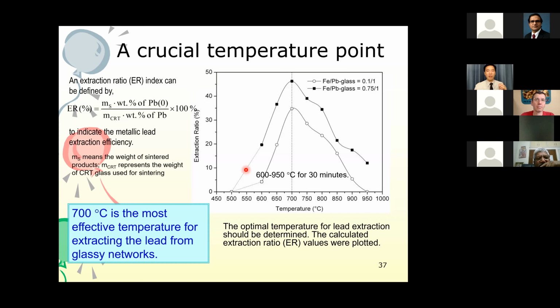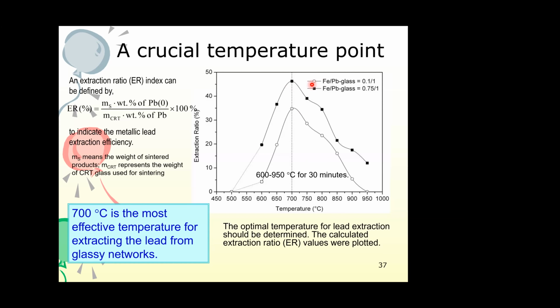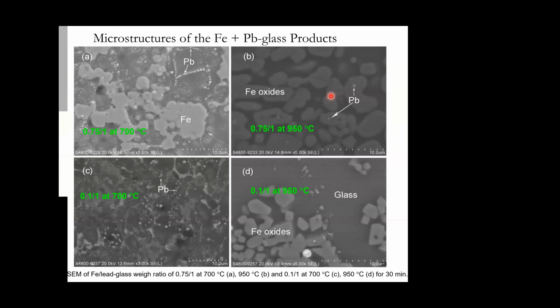But in order to control this process, to know potentially how much lead you can recover within one run of operation, then you need to use the quantitative method. So in this case, we figure out the best concentration, best temperature is around 700 degrees Celsius. Don't use too high temperature or too low, and you also have a certain amount of the lead and iron ratios. You don't want to put too much ratio. This gives you probably a little bit more a realistic feeling.